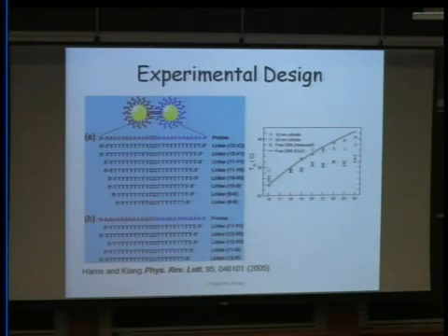The total is 24 bases. If it's shorter, like 23, 22, then in free solution, the shorter it gets, the lower the melting point will be. But when these DNA are attached to the gold particle surface, and sometimes similarly with other surfaces, the melting points actually change unexpectedly. In this case, it goes like a zigzag, up and down.